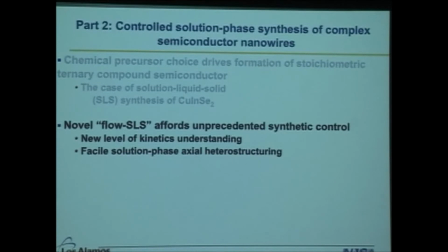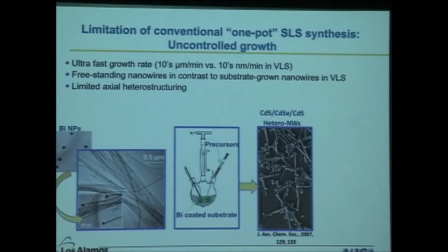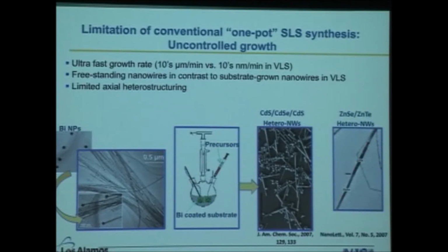So we sought effectively to do two things. Allow us to slow down the growth process, to be able to really study kinetics in this system and get some fundamental understanding of the growth process, and then also to create an easier way to make axial heterostructured nanowires. A couple of examples in the literature: this is the Park group at Harvard, where they took a bismuth-coated substrate, put it in a flask, added precursor, washed the substrate off, put it in another flask, added the next precursor, and they could do this a couple of times and get these cadmium sulfide, cadmium selenide, cadmium sulfide heterostructures. But it's a multi-step, fairly tedious process, and it's clearly not going to get you all that far in terms of the number of segments.